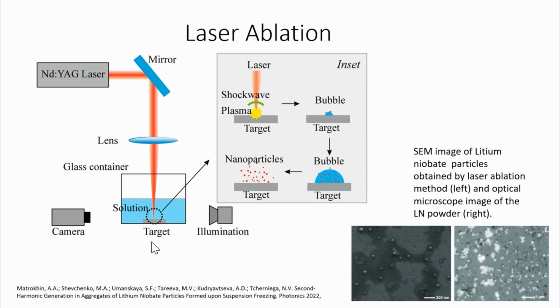The intense electrical field of the laser beam ionizes the vapor. A supersonic jet of evaporated material, a plume, is ejected perpendicular to the surface of the target. The temperature in the plume reaches values of 3800 Kelvin and more. During the adiabatic expansion of the plume, the temperature decreases and as the vapor gets supersaturated, particles are nucleated. Within the short time interval of supersaturation, the particles are formed. Here you can see some examples of particles obtained by laser ablation and the process of how to obtain the nanoparticles using the technology of laser processing.